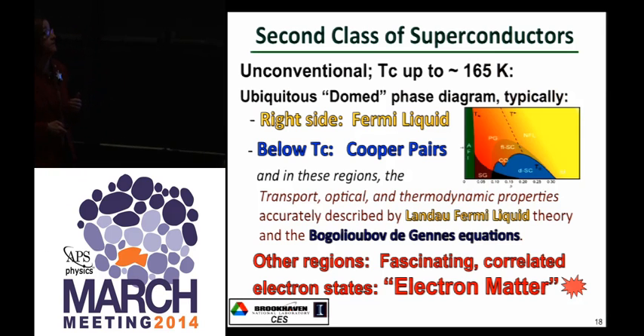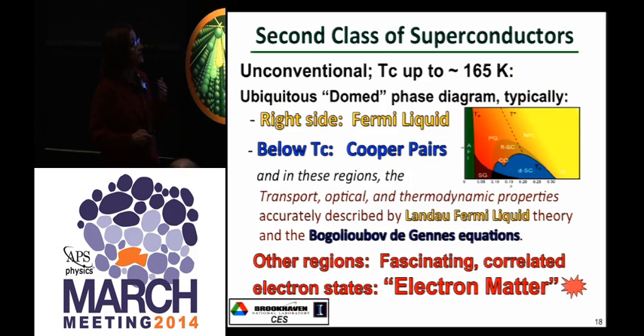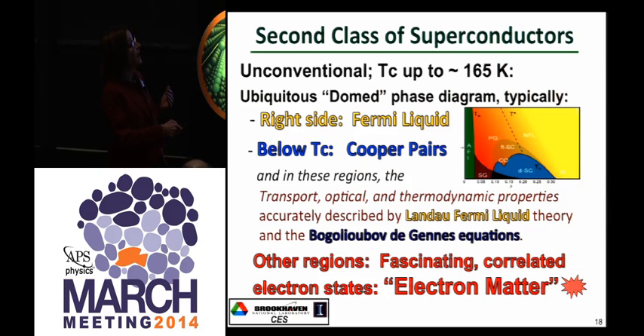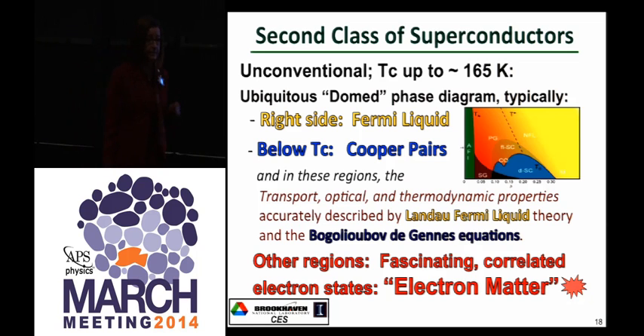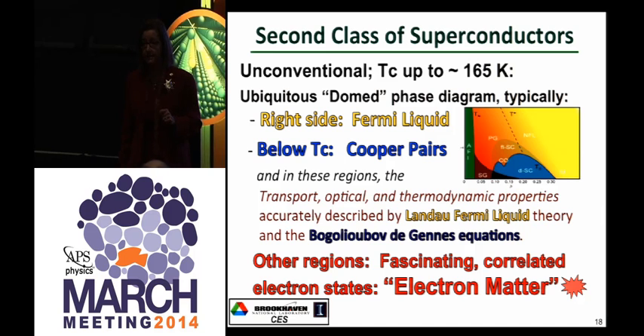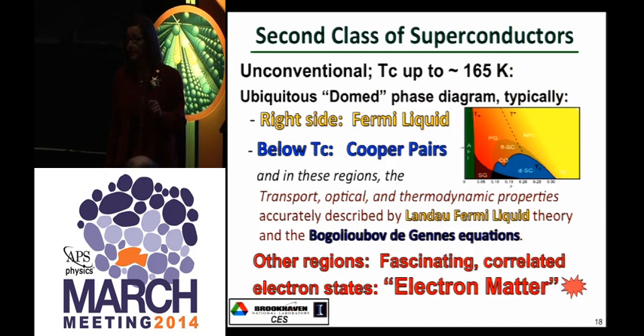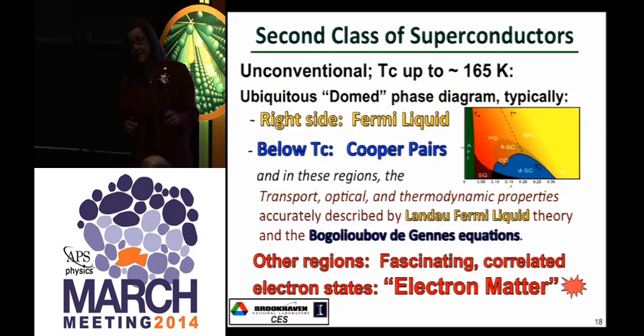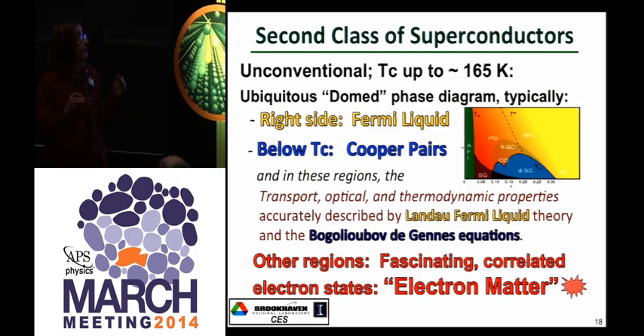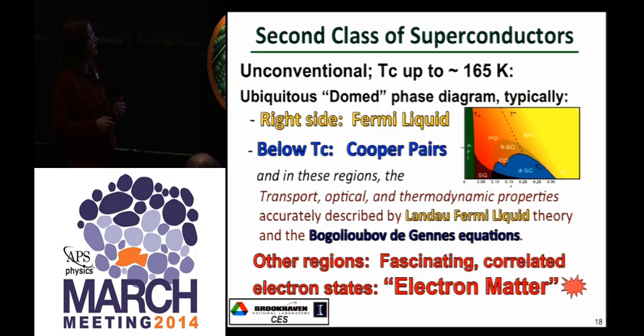Now, here's what we have for our unconventional superconductors. Temperature is much higher, and there's the ubiquitous dome phase diagram. Typically, as I mentioned before, because I want to repeat it, on the right side is the Fermi liquid, and below Tc is the Cooper pairs. And I'm going to use the same line I used in the last viewgraph, which is, in the Fermi liquid side and under the superconducting dome, we pretty much understand this. You might have to put in an order parameter symmetry. When you have multi-band materials, it makes it a little more complicated. But pretty much we can describe the optical transport and the thermodynamic properties under the dome. But the other regions is what I'm calling electron matter.